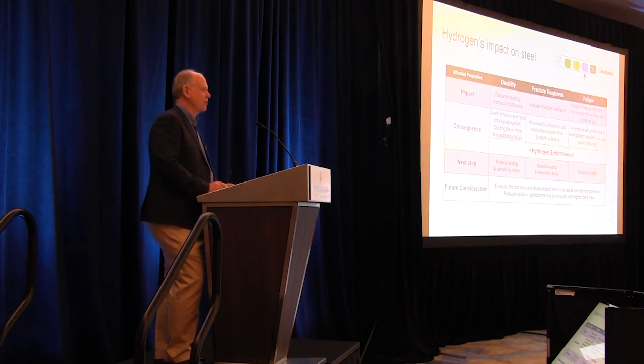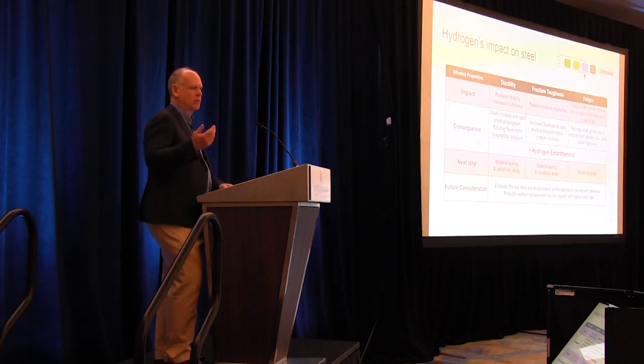The interesting thing that I found out working through hydrogen is that for hydrogen embrittlement, stress is a big factor, and it's changes in stress. And we always think in business about changing pressure. So the pressure changes, the stress changes. But even if the pressure is constant, if you've got external stresses acting on that vessel or that piece of pipe, that actually creates changes in the stress environment and can lead to crack growth, even though you're keeping your operating pressure constant.